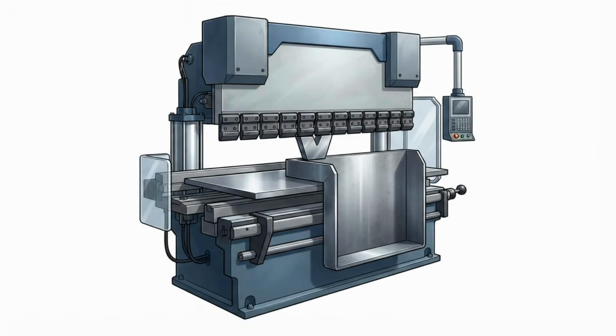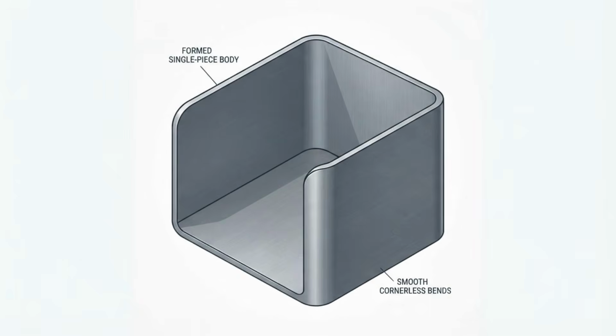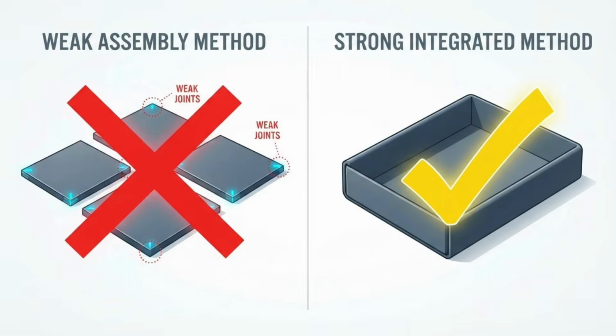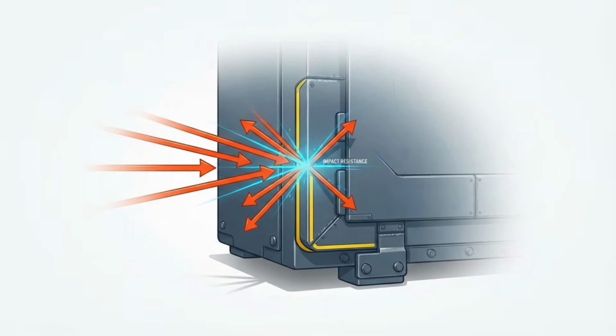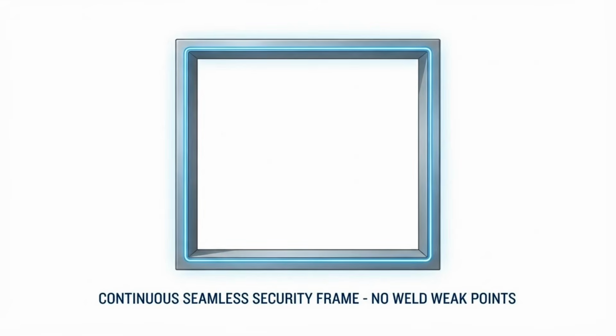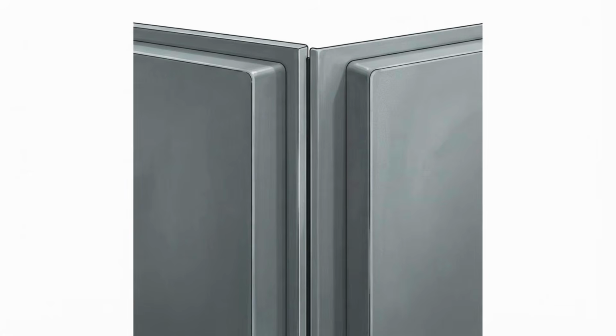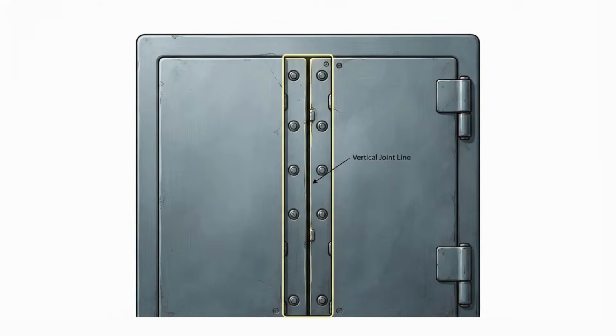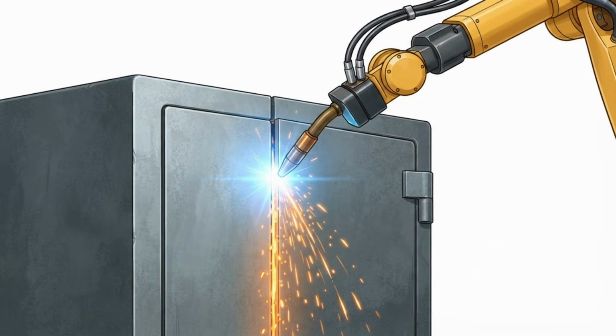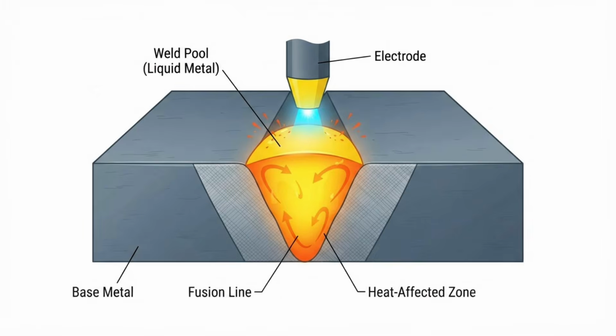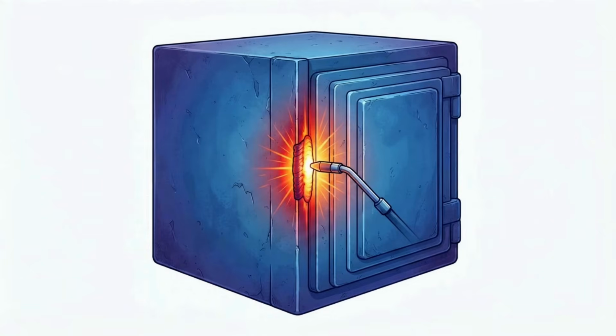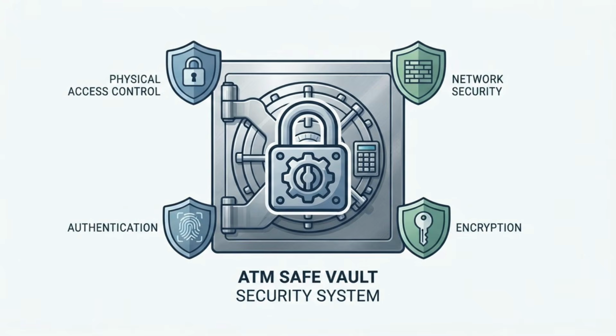of the safe. Bending the steel into a box shape, rather than welding multiple flat pieces together at the corners, significantly increases the structural integrity of the vault because it eliminates vulnerable seams. However, where the bent panels ultimately meet, seams are unavoidable. Robotic arms perform continuous gas-metal arc welding along these joints, ensuring deep penetration of the weld pool without overheating and warping the surrounding steel.